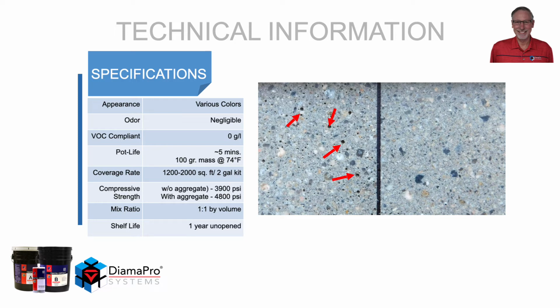Compressive strength, 3,900 psi without aggregate and 4,800 psi with aggregate. It is a 1-to-1 by volume mix, and the shelf life is 1 year in an unopened container. In the image, you'll see the arrows on the left are showing small little pinholes on the surface, and on the right there are no pinholes. So the left was left ungrouted and the right was grouted.